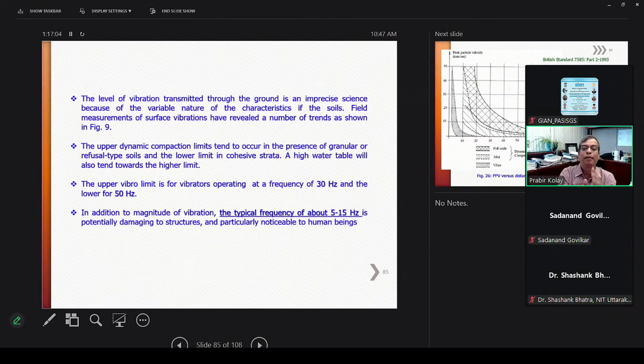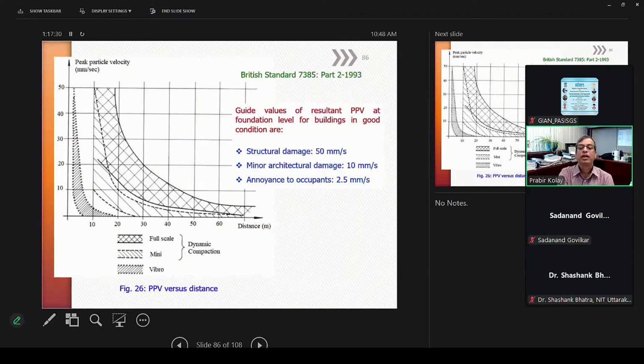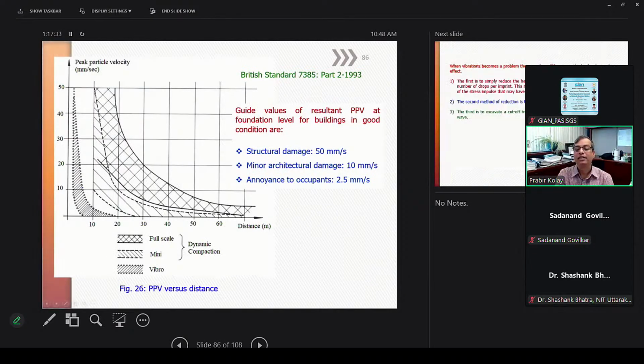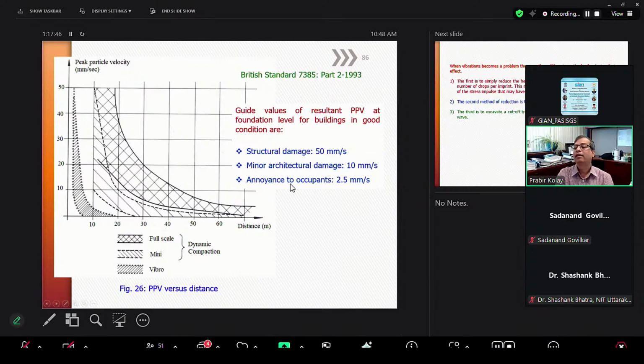Over here you can read that. The upper vibration limit of the vibrating operator is frequency 30, and the lower is 50 hertz. This is the limit generally used. In addition, for the magnitude of vibration, a typical frequency range of 5 to 15 hertz is potentially damaging to structures and particularly noticeable to human beings. So basically, the lower frequency is not good. This will also give you some guide. Here is the same thing again, the structural damage. Earlier I mentioned 50 millimeters per second. Minor architectural damage occurs if the peak particle velocity is 10 millimeters per second. Annoyance to occupants in an existing building is at 2.5 millimeters per second.